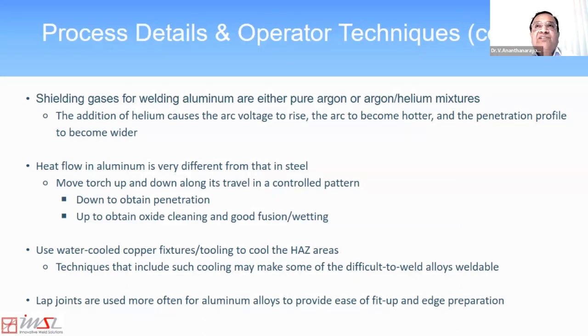One of the techniques I have seen folks do, such as those who weld aluminum gasoline tankers in Tennessee, is they do the welding manually. They don't do it using a robot. As they are traveling along the weld length, they maintain the same push angle and the same travel speed with their hands, but their hands are going up and down as they go along the weld. When they go down, they get penetration, and when they come up, they get cleaning and good fusion, good wetting.